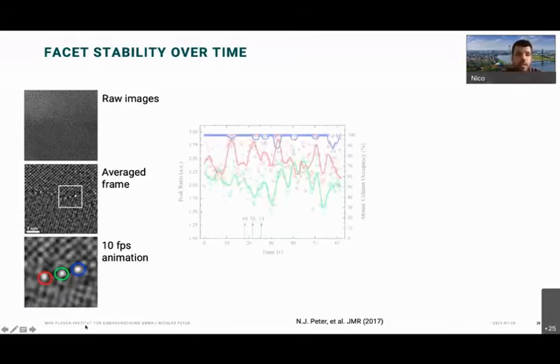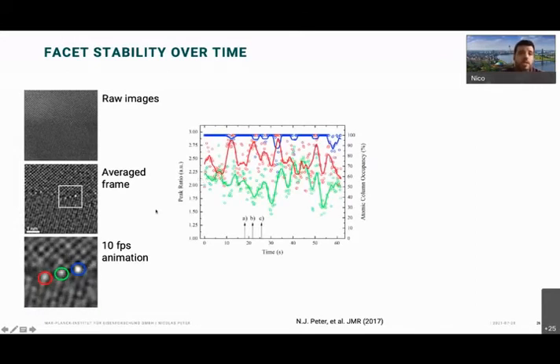So we extracted here the actual peak ratio, so the intensity peak ratio, how much intensity we have in the bright column here. Oh, should switch back again. How much intensity we have in this column here versus the bulk. And this is related to the HAADF Z-contrast imaging conditions, then correlated to the atomic column occupancy. So how much silver is in one atomic column at the grain boundary here.